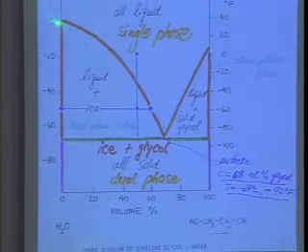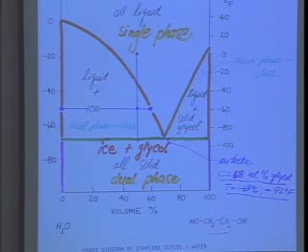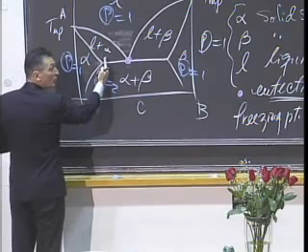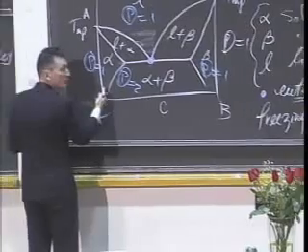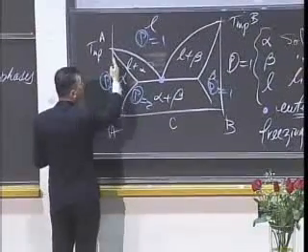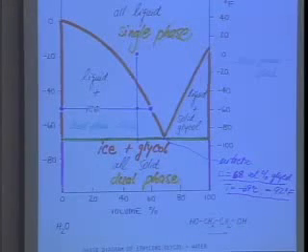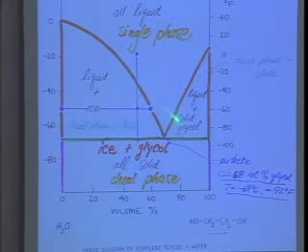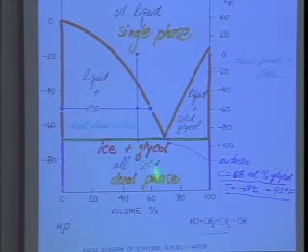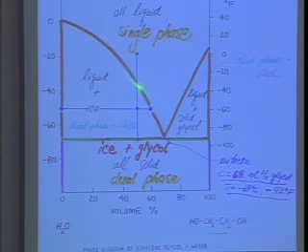And so pure water, we see the melting point of pure water is 0 degrees C. And what this is showing is that this alpha region of ethylene glycol and water is so narrow that for all intents and purposes this appears as a straight line. That's why you go automatically from seemingly pure water to this eutectic regime. So if we add typically about 50 volume percent ethylene glycol, that's the recommended mixture, what do we see? We see we get freezing point depression down to about minus 35 or so Celsius, which ought to take care